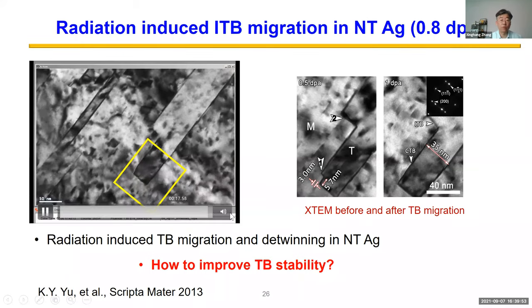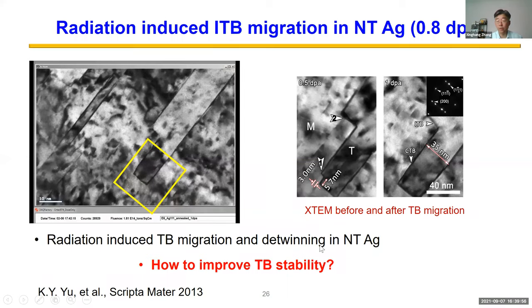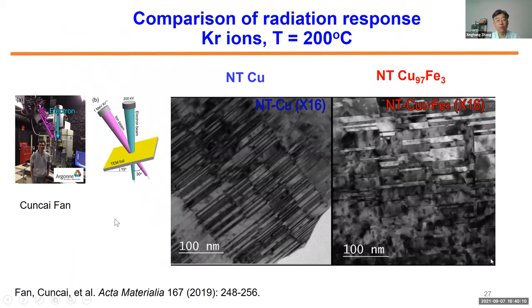So this rapid twin boundary migration event is interesting, but can be of a concern because if twin boundary evolve, if detwinning happens, then you don't have twins, then what happens? And the metal become classical metal again. You don't have a lot of this defect sinking. So to stabilize twin boundaries, one of my former students, Cuncai, he designed an interesting experiment. He was comparing nanotwinned copper, again, cross-sectional view, with copper doped purposely with 3 atomic percent of iron. So now he added 3% of iron in copper and performed the same kind of radiation in parallel.